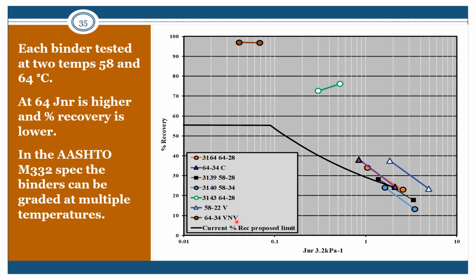Some of the similar binders here, you see them tested at 2 different grades, temperatures, 64 and 58. And if we look at these, in this particular case, these 2 binders here, this is a 5828 and this is a 5834. When they're tested at 64 degrees, they would still meet a 64S grade. However, when they're tested at 58, now they have both dropped down to the 58H grade. This particular one here, which is a 58 minus 22, at 64, you can see it doesn't even meet an S grade now. It's significantly softer, but it will meet a 58H grade, just barely. It's just at the limit, at just under 2.